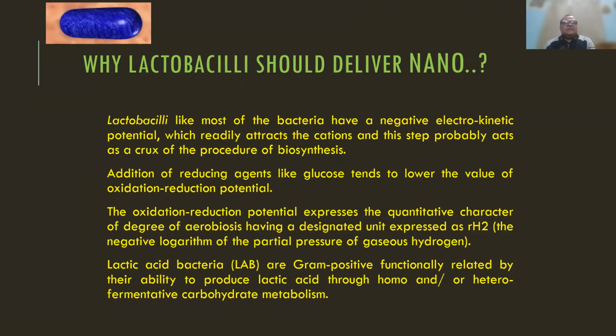So now let us reason with lactobacilli. Why should lactobacilli deliver nano? Lactobacilli, like most of the bacteria, have a negative electrokinetic potential, which readily attracts the cations, and this step probably acts as the crux of procedure for biosynthesis. Addition of reducing agents like glucose tends to lower the value of oxidation reduction potential, which we generally add, we manipulate, we play the game with glucose. So I'll open up a little bit later on.